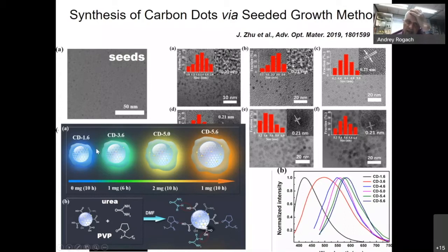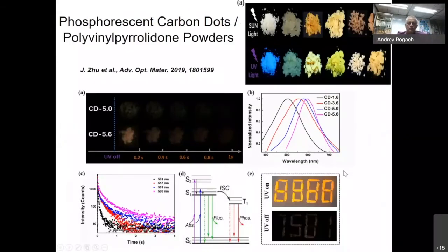And here the color of light will also change depending on size. Actually, we can call these carbon quantum dots eventually. And you can see how emission will move from blue emitting materials to red emitting materials. And very interestingly, when we dry these solutions, we can get powders very easily, quite a lot of them. And these powders will have different color under sunlight. And if you put UV light to excite these colors, you can see they all emit different color of light.